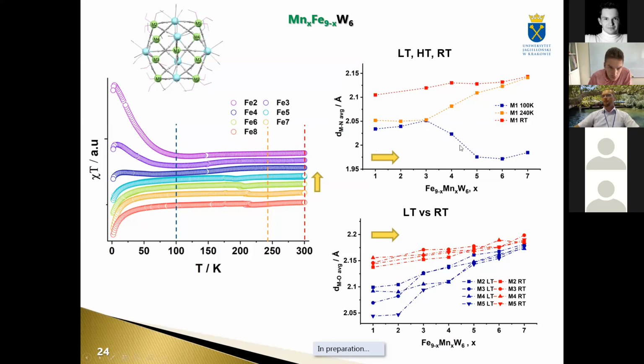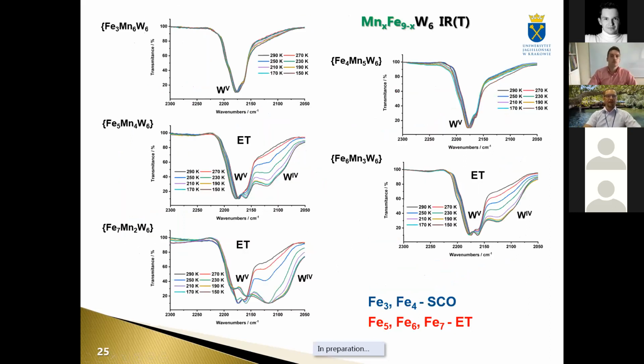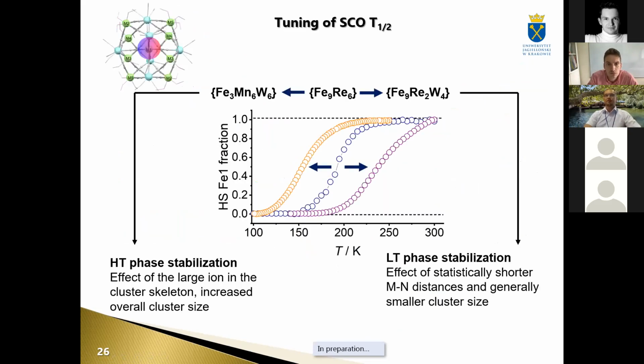But here we have a sudden drop, and in the manganese-rich phases, here we have something which looks like iron-2 low spin, which supports our suggestion that here we have spin crossover and here we have electron transfer. Again, with IR data, we are able to confirm this data. The main conclusion from this